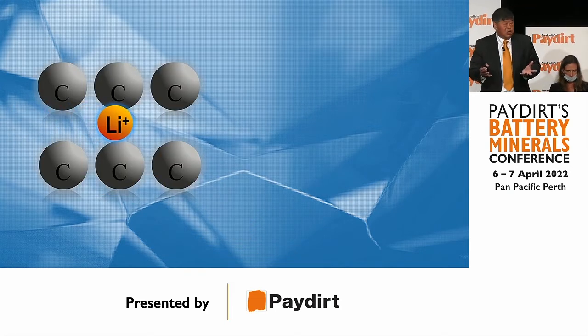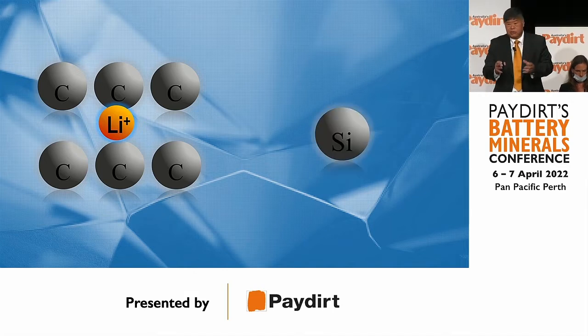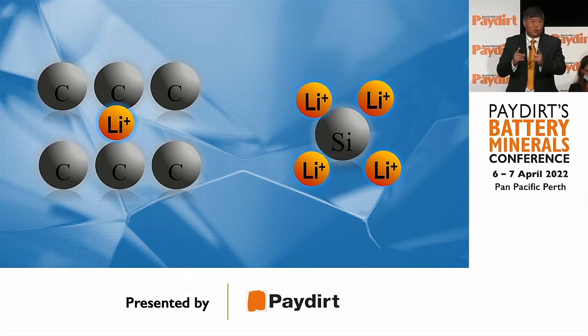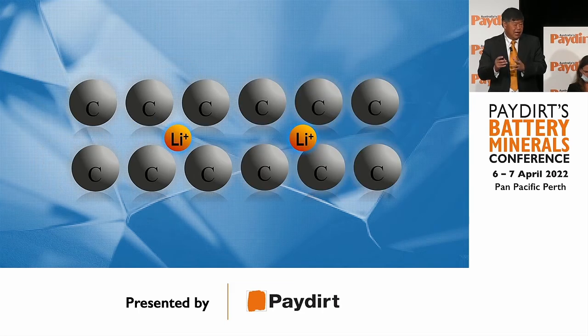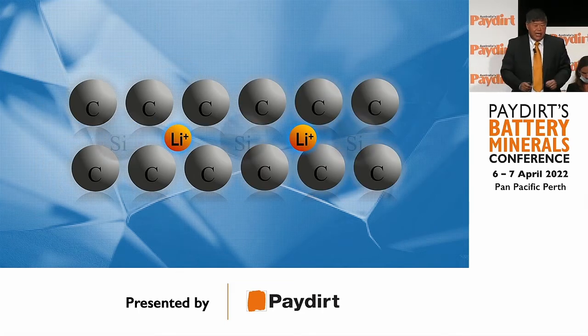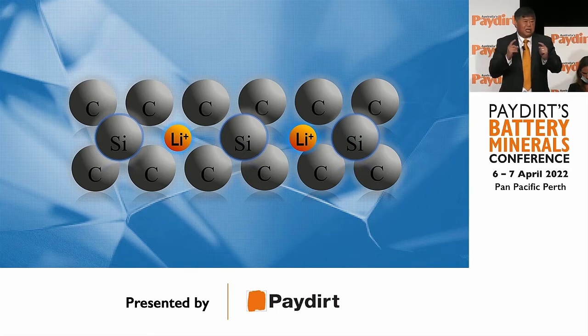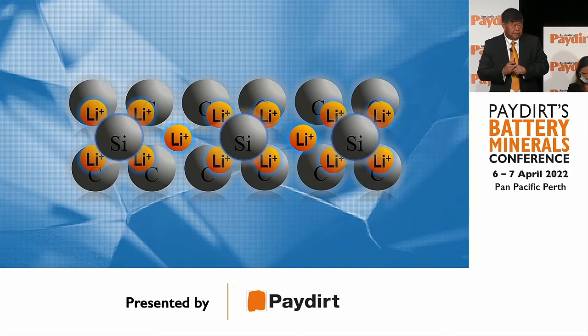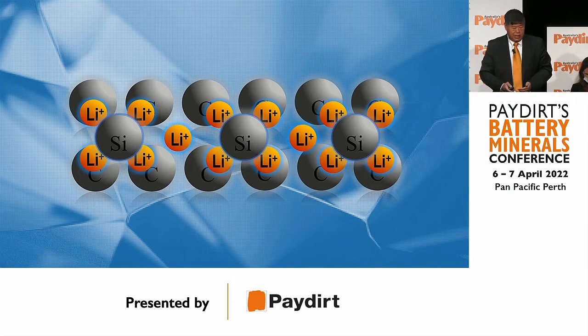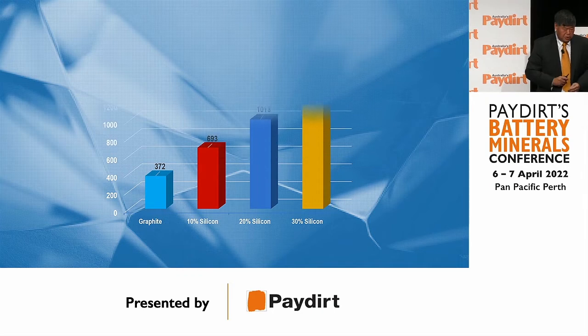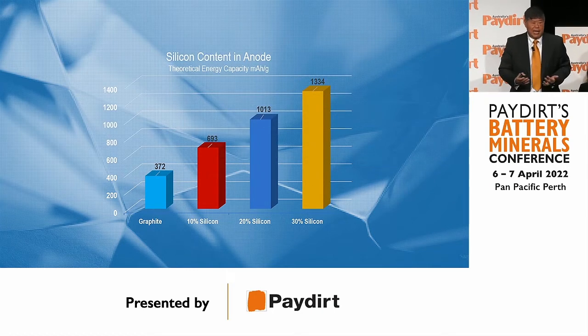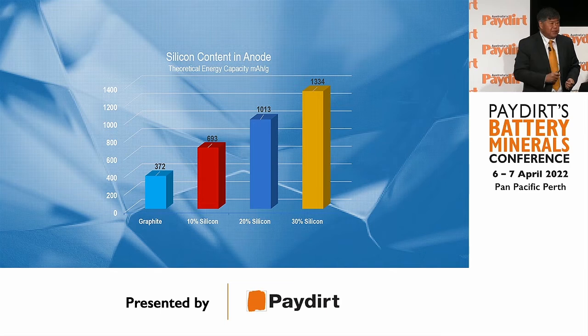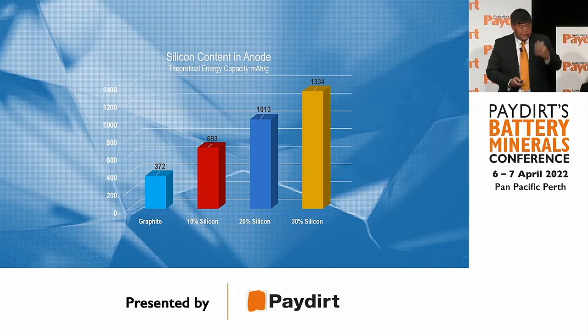Now, let me tell you the potential of silicon. It takes 6 carbon atoms to hold 1 lithium ion. It only takes 1 silicon atom to hold 4 lithium ions. Now, if this was an anode in a battery and you put some silicon in it, this is how much lithium that battery can hold. You can see the potential of getting silicon in an anode of a battery. Today, graphite is around 370 milliamp hours per gram. If you can add 10% in that battery, it nearly doubles the energy capacity. Add 20%, it nearly triples it. And if you add 30%, it goes up to about 1,300.